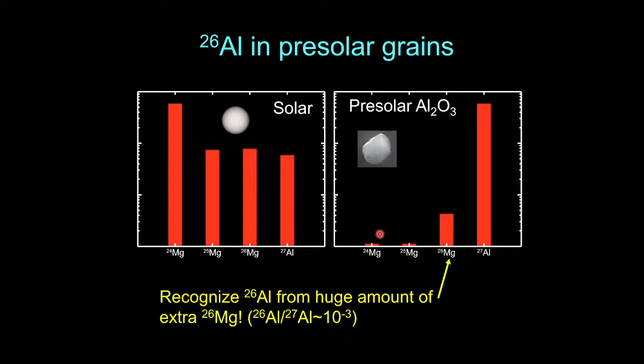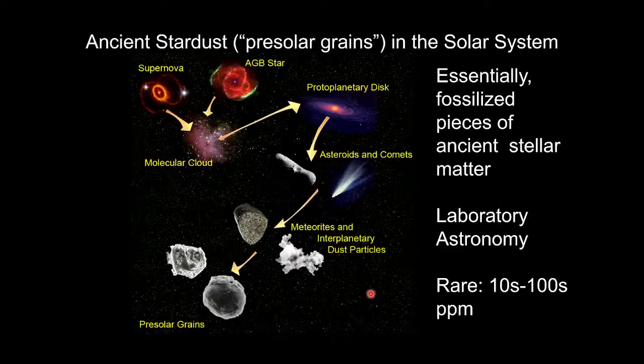So that's a clear sign of radioactive decay, that this magnesium was once aluminum, and we can calculate that the ratio of aluminum-26 to 27 was about 1 in 1,000. We can compare that with what's expected for AGB stars and learn more about the nuclear processes happening in that parent star. So that was a little cartoon to tell us how we know we have presolar grains and the history of a single grain.